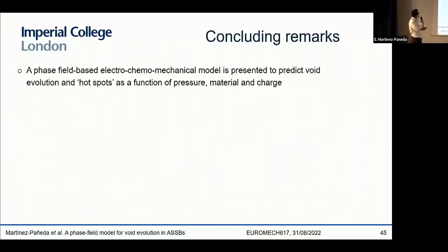Excellent. So I just want to say that our goal was to develop a phase field-based framework that combines the phase field paradigm, to capture arbitrary evolution of the morphology of those voids, with a mechanistic electro-chemo-mechanical model that describes, at the continuum level, all the atomistic phenomena happening during this process. And I think the model does a good job of predicting the void evolution and the hotspots, at least qualitatively. We can capture those as a function of pressure, material, and charging conditions, both magnitude and loading history. We can do this for multiple loading cycles.